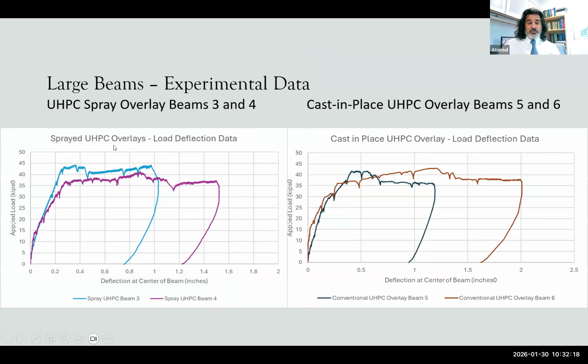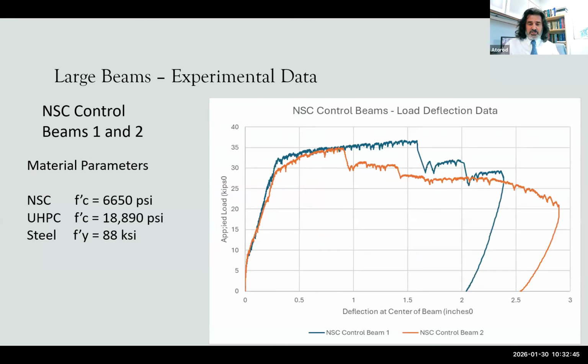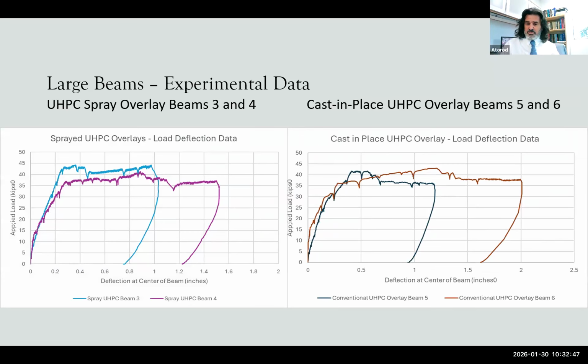Then we sprayed it with the UHPC about an inch and a half, or companion cast in place. First of all, there is no difference between the spray or cast, because both of them give you about, let's say, 45 kips. In fact, spray gives us a little bit higher, and ductility didn't change or anything, but 45. So you can see that the capacity increased from 35 kips to 45 kips by just spraying or casting UHPC on the bottom, on the tension side.